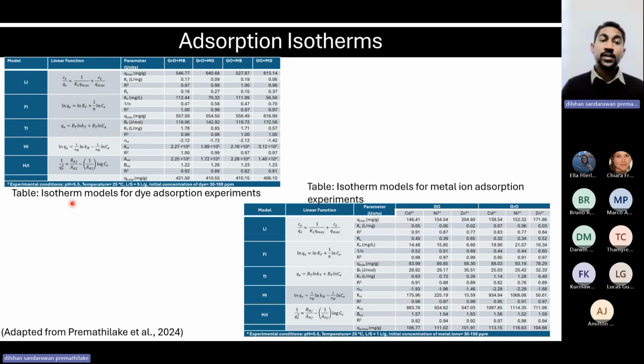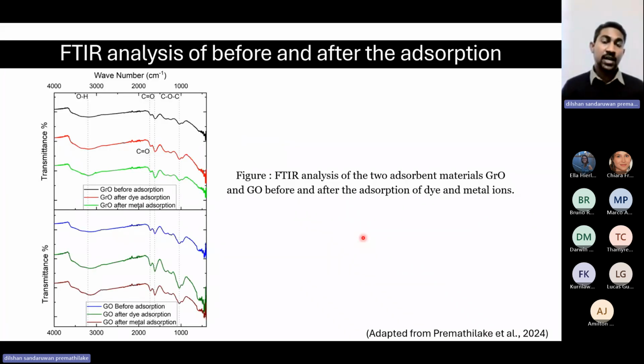And then we did FTIR analysis before and after the adsorption to further understand the mechanism of the adsorption. The first part is the graphene oxide. Before the adsorption, most of the surface active sites, like the carboxylic group and the hydroxyl group, are visible. After the adsorption of dye and of metal ions, the transmittance in these regions is quite low. This is due to the adsorption of the material onto these surface active groups. However, the metal adsorption shows a smaller change than the dye adsorption. Same pattern here: for the dye adsorption, the transmittance is really low, but for the metal adsorption, it is not as low.